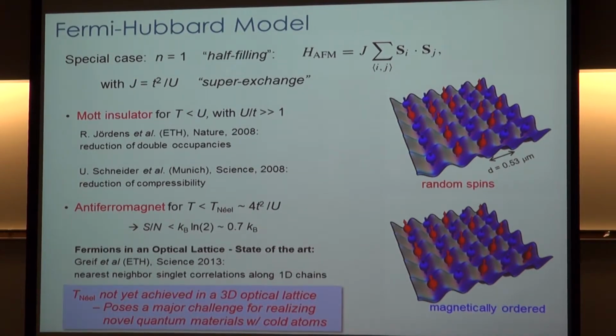We talk a lot in our field about how we can get to ultra low temperatures, but in reality, we should really be talking about the ratios of the temperatures that we can get to the Fermi temperature. The Fermi temperatures in real materials are like 10,000 degrees Kelvin. And the Fermi temperatures in our system are like a microkelvin. So the temperature scale is different by what is that, 10 orders of magnitude. And so in order to get to a similar temperature scale in ultracold atoms, we have to lower the temperature by 10 orders of magnitude. We have to get to some small fraction of a microkelvin, so like nanokelvin. And so this has been a real challenge.